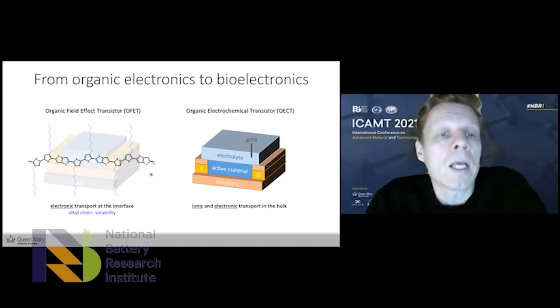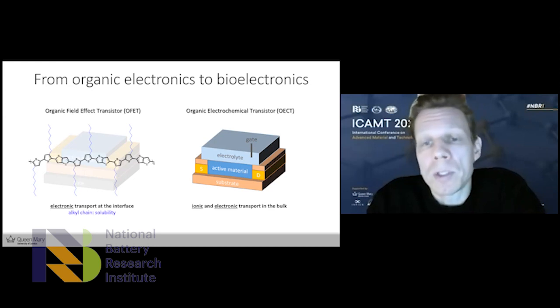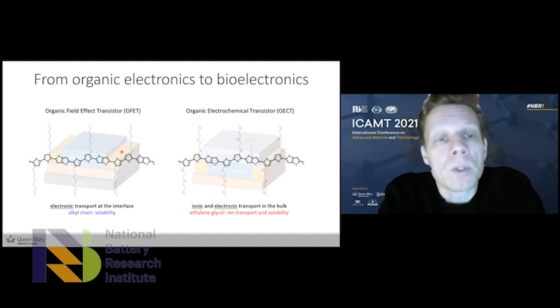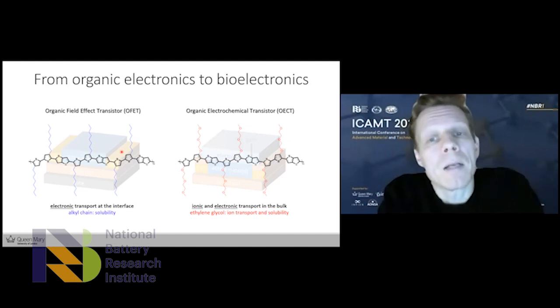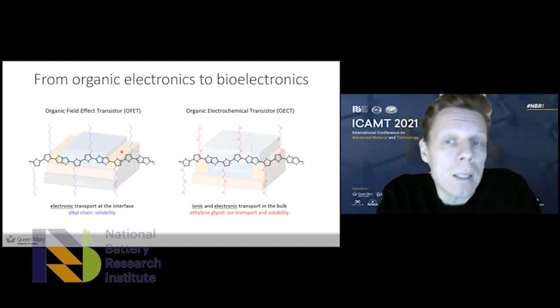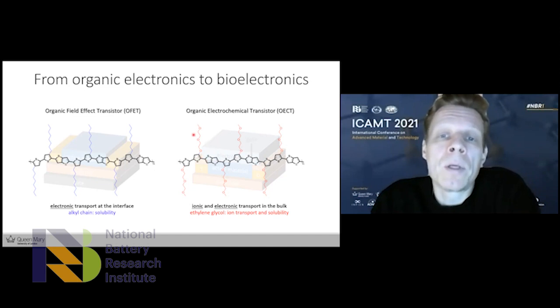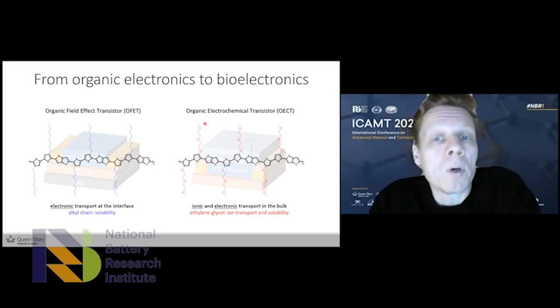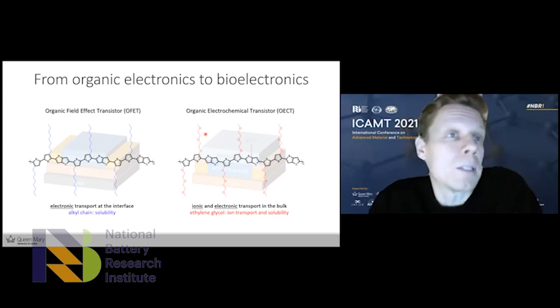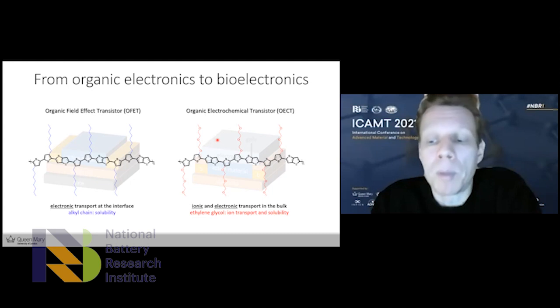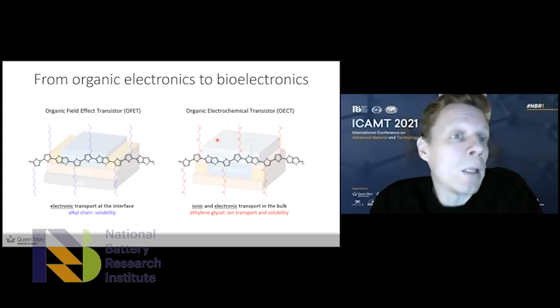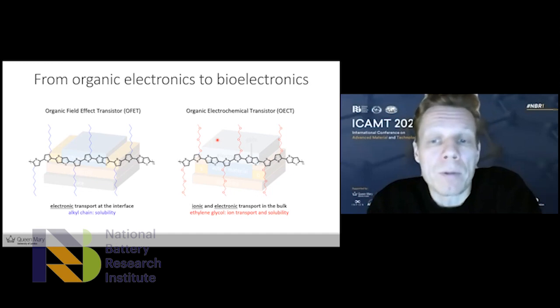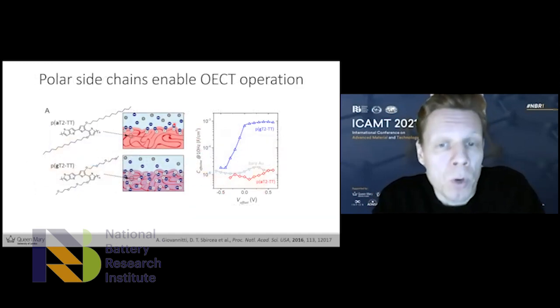So we were thinking along the same lines: how can we modify these materials to then work in an organic electrochemical transistor? And what we came up with was substituting these alkyl chains, the aliphatic chains, for solubility. We decided to make them much more polar, so we added these ethylene glycol chains rather than the alkyl chains onto the polymer backbone. These much more hydrophilic and polar side chains, we were hoping that they would facilitate ionic transport in the film, in the bulk film. So allow the material to swell in water, and then the ions can move in and out of the film. That turns out to work quite well, actually.